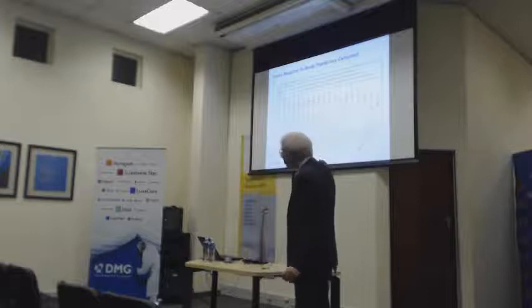So when you have enough walls to bond to, when you have enough structure and the proper combination of bonding agent and core material, you don't actually need to place a post. This is dogma, this has been overcome. And if we look at the differences here, you can see this is about 15% that you're gaining in terms of fracture load. But the tooth has not lost any structure, and the tooth itself is strong. So this is an interesting thing to look at, restoring teeth with a post.